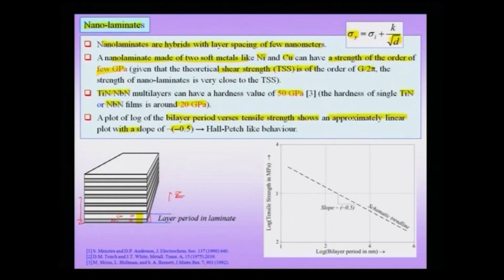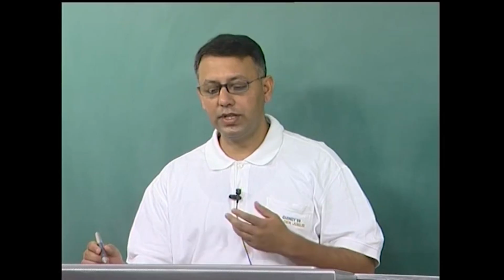That means that now if I am plotting log bilayer period versus the log of the tensile strength, I find an approximately linear plot which shows a slope of minus 0.5, which means that we are seeing an effect which is very similar to the Hall-Petch effect. That means that in the Hall-Petch relationship, we originally pointed out that typically we plot yield stress, and yield stress follows this relationship. We had extended to say that even hardness follows this relationship. Now we are saying not only is the grain size d which follows this relationship, but could actually be a bilayer period in a nanolaminate or in a laminate structure.